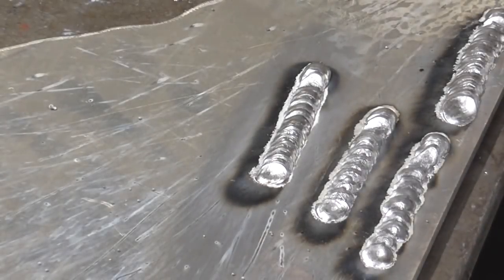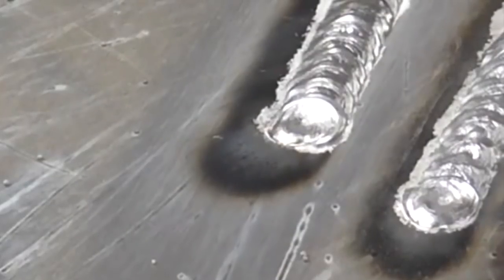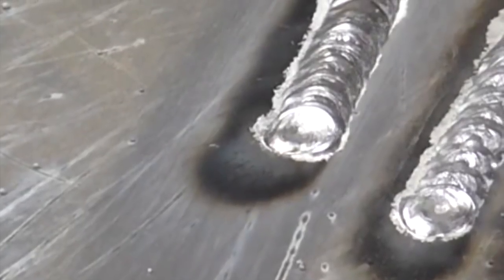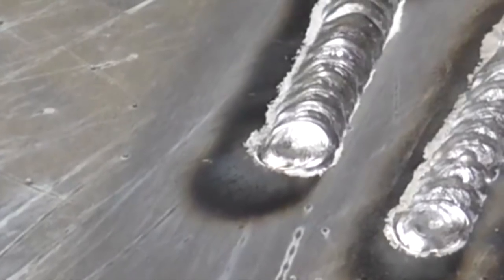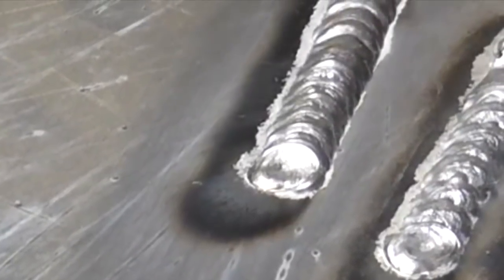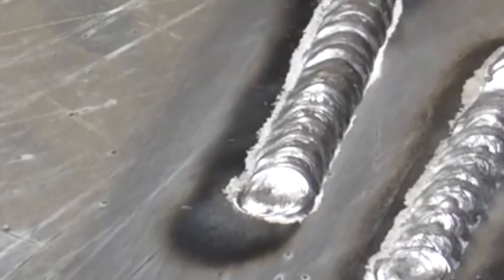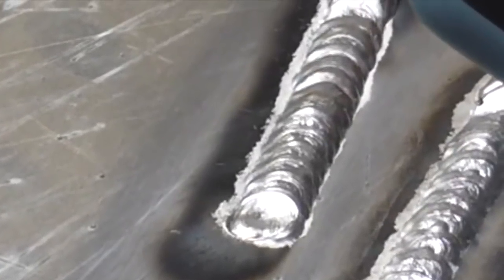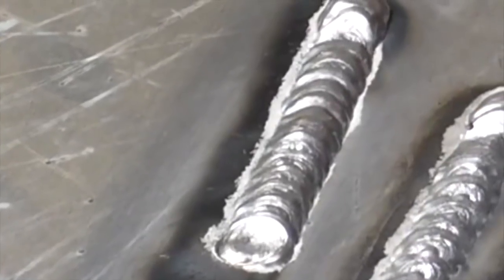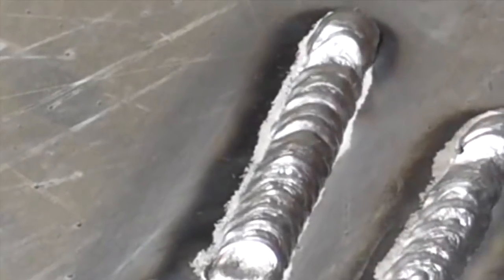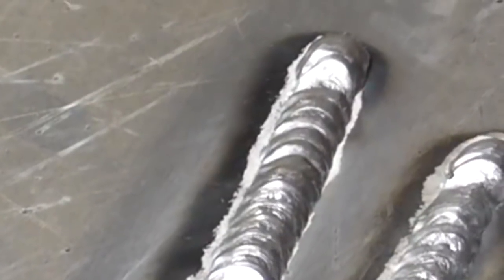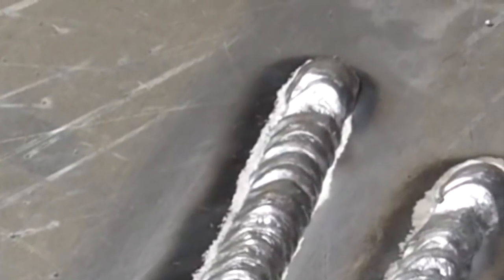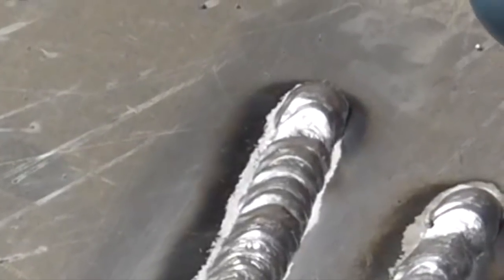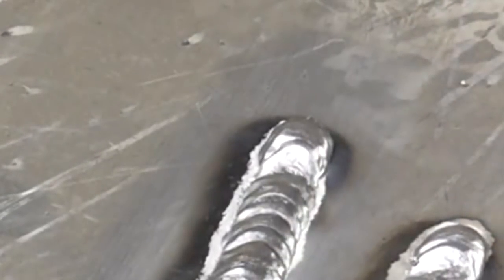That was a good one, yes. So apparently, I finally did a good weld here. So you see the one that I cleaned the material with the wire brush just briefly. I didn't go crazy on it, and I didn't acetone wipe it. But you see the difference to the right side, about the same travel speed, the exact same settings, similar material thickness. Yes, it got a little bit warmer with the fourth weld instead of the third weld, but that was not really the main part here. Just cleaning the oxide layer helps a lot as far as consistency and bead appearance and penetration and all these good things. So aluminum does take a little bit of cleanliness.